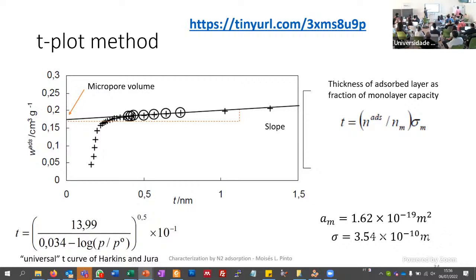And in the t-plot method, what we put in here is essentially the adsorbed amount over the adsorbed amount in a monolayer times the sigma of the molecule, so in this case, the cross-sectional area that we have here. There are many proposed equations. One of the most used ones is this, which relates this thickness with P over P0.